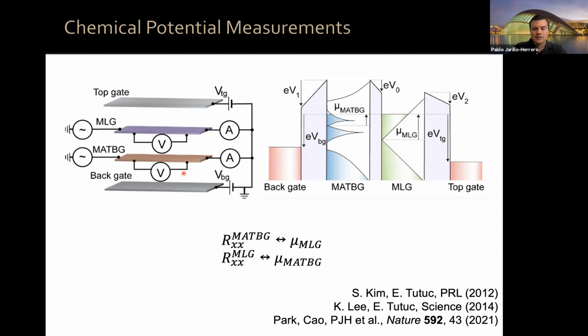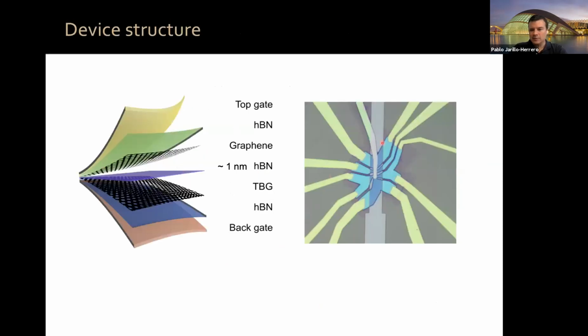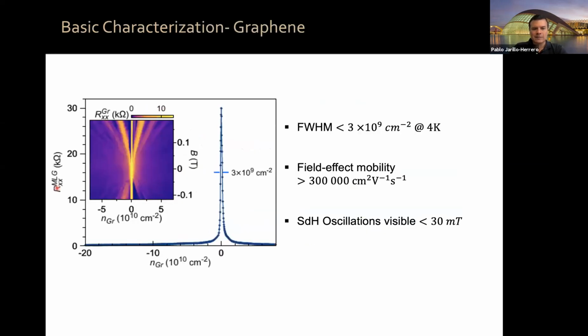The device structure, as I said, this is an optical picture. These devices are quite complicated, but you have back gate, hexagonal boron nitride, magic angle graphene, a 1 nanometer or so, 2 nanometers of hBN, then the graphene sensor, then again hexagonal boron nitride, and the top gate. So this is the resistivity of the monolayer graphene as a function of charge density in the monolayer graphene. It's a very high quality graphene sensor with a field effect mobility much higher than many hundred thousands, with onset of Shubnikov oscillations at 30 millitesla.